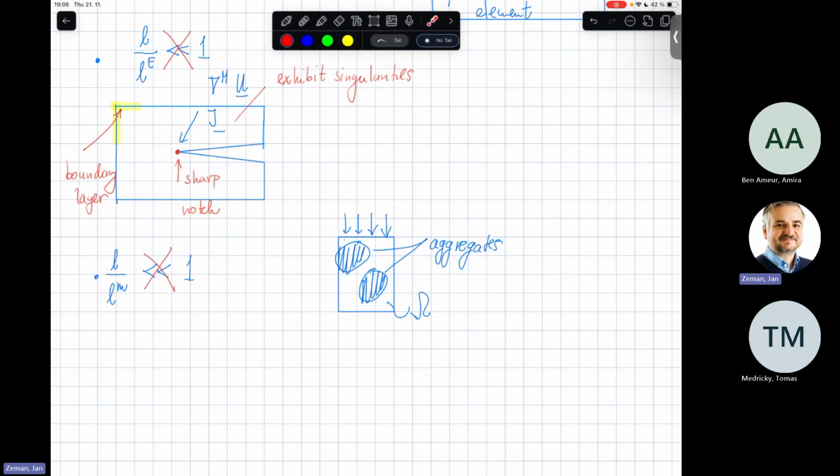So this is just an example, and sorry for my childish drawings, but certainly you can find some additional experiments. So in this case, indeed, you should somehow take into account that you are not using homogenized, not using effective properties, but apparent ones, and at minimum you can get these apparent values by solving these two problems, or performing these two types of mental or real experiments, and this gives you roughly the range in which your homogenized response, your apparent response, will eventually be located.